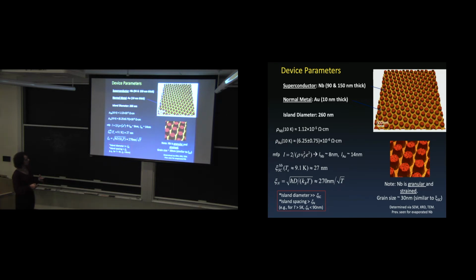at 10 Kelvin, the island should be coupled at around 100 nanometer spacing. Okay, so when the niobium goes superconducting, if the islands are closer than 100 nanometers, they should immediately couple. Otherwise, we have to lower the temperature before they can couple.